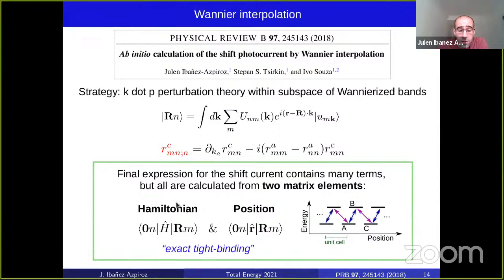One is the matrix elements of the Hamiltonian in Wannier basis. By analogy with tight binding, this would be the on-site and hopping terms, and this fully describes the energetics of the problem. For instance, they are enough to give the energy spectrum. But we also have matrix elements of the position operator, and this is perhaps a bit less familiar, since again, if we think of tight binding, in tight binding, position is diagonal. The position enters only, it just marks where the orbitals will sit. But in the Wannier formalism, we have the full off-diagonal structure of the position operator in real space. In that sense, it's a sort of exact tight binding model. And as we will see, this description will be important in capturing the shift undergone by the electron when it's photoexcited.